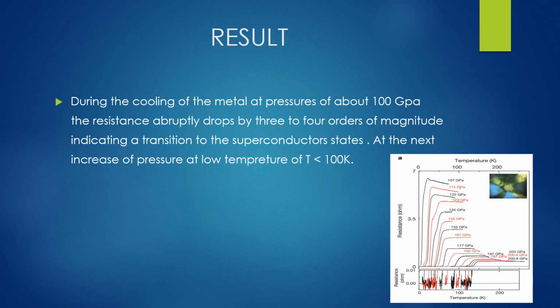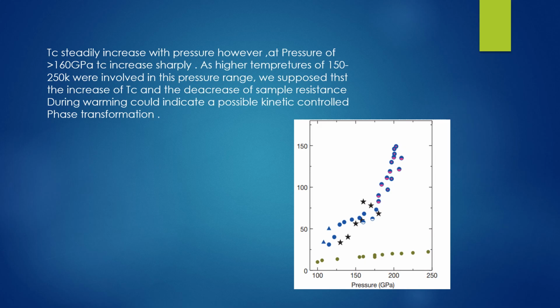Now next is the result. What are the results obtained from the superconductor we made? Firstly, during the cooling of the metal at a pressure of about 100 gigapascal, the resistance abruptly dropped by 3 to 4 orders of magnitude, indicating a transition to the superconductor state. Then the pressure was increased further at low temperature, T less than 100 Kelvin. This graph shows the variation of temperature and resistance. Tc steadily increases with pressure.